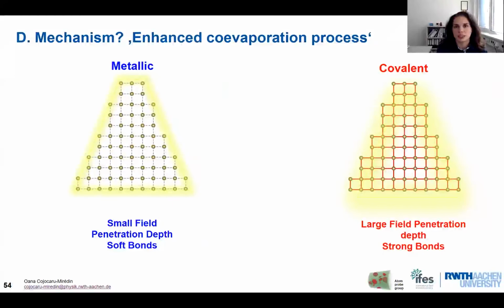So now let's explain why we have an enhanced coevaporation process taking place for this particular class of materials. And to explain that, I have shown here two main compounds which are widely used during the atom probe experiment. So we have the metallic compounds. For the metallic compounds, we have in general a very small field penetration depth. We have learned that during this lecture. And the metallic bonds are also very soft. But this altogether leads to pretty low multiple events of about 10 to 20%.